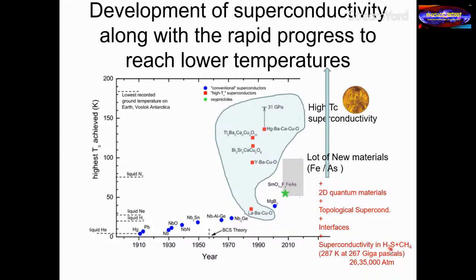This is in hydrogen sulfide, carbonaceous hydrogen sulfide, a mixture of hydrogen sulfide and methane at very high pressures, of around 267 gigapascals. Just to give you an idea, if 1 atmosphere is the atmospheric pressure around us, 267 gigapascals is like 26 lakh atmospheres. So these are very, very high pressure experiments. But at high pressures, this gas and this carbonaceous mixture liquefies, solidifies, and then actually becomes superconducting.